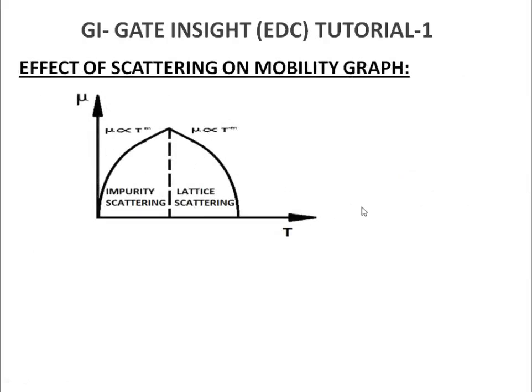Now the effect of scattering on mobility graph is given as this. We can see that as the temperature is increasing, first, because of impurity scattering with less impurity, there is a relation mu is proportional to T to the power of M. So first the mobility increases. Then, as the temperature further increases, there is oscillation in the atoms, and because of that the mobility decreases. So mu is proportional to T to the power of minus M for lattice scattering. For impurity scattering, mu is proportional to T to the power of M, and for lattice scattering, mu is proportional to T to the power of minus M.